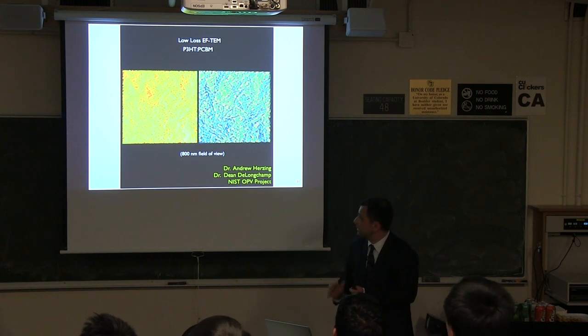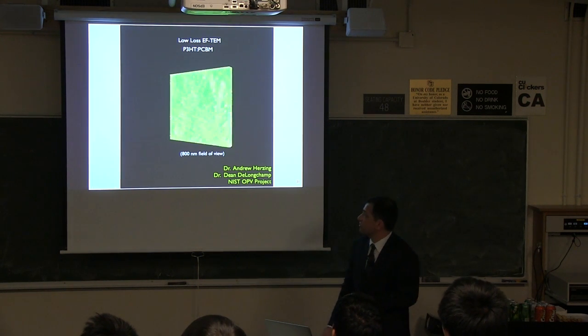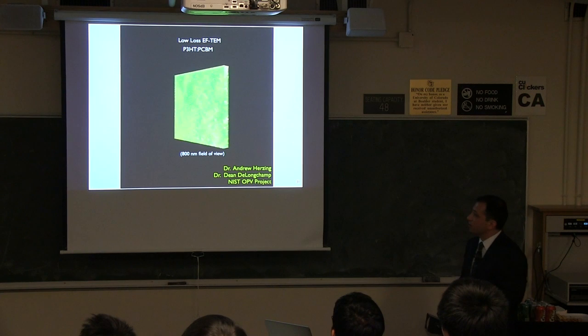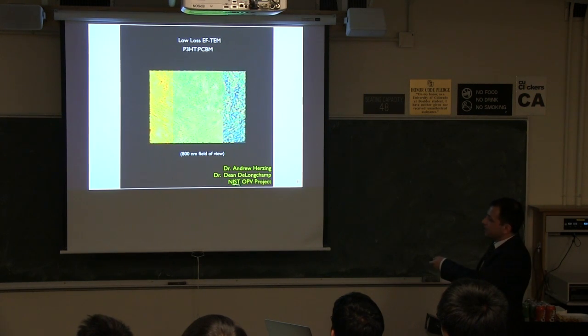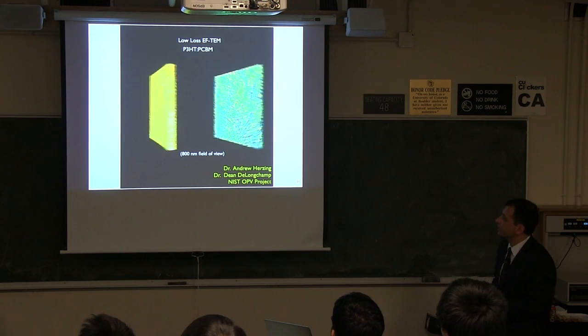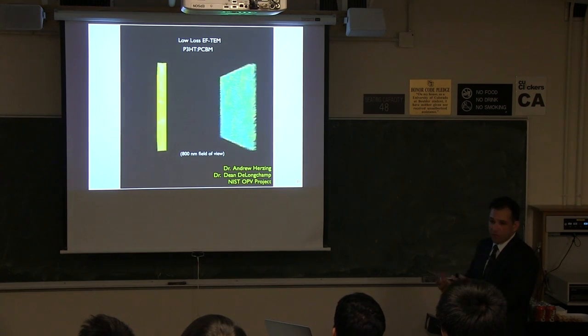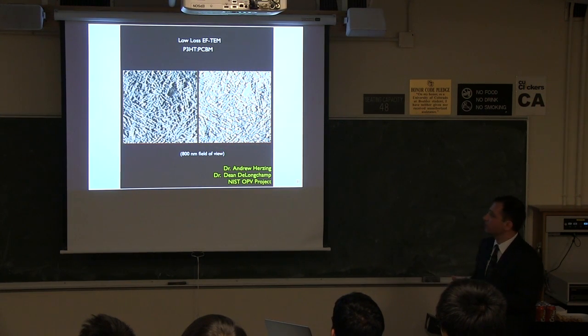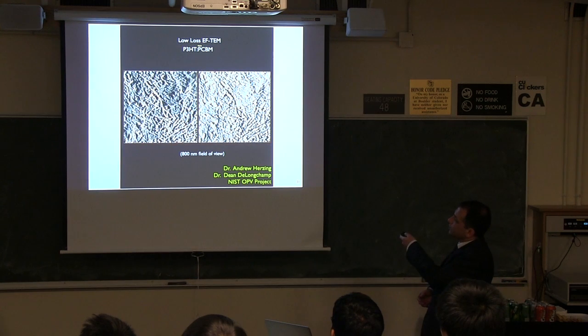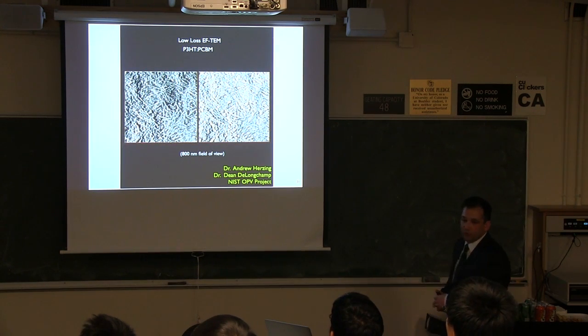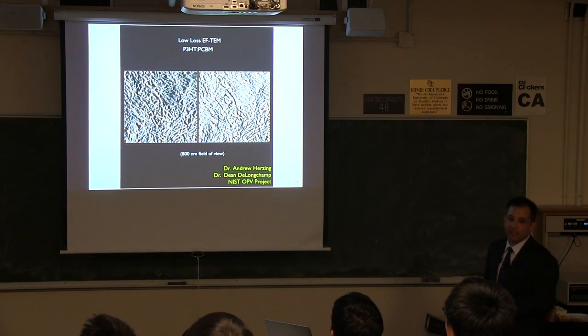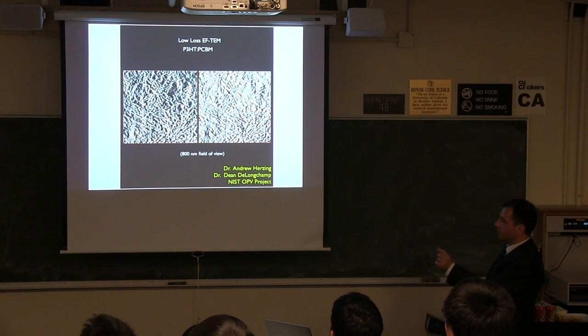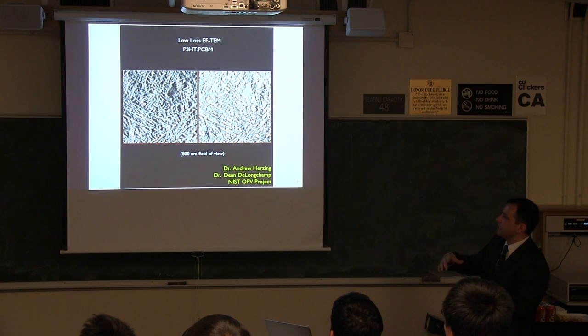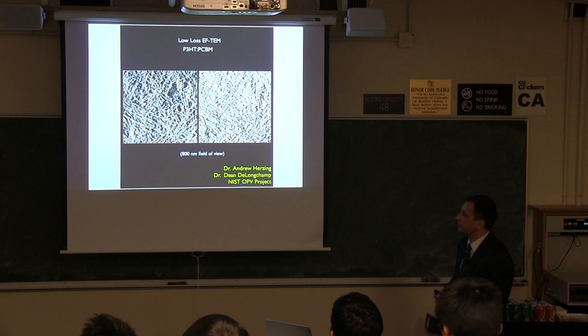So I mentioned that the mixing is very important, and the three-dimensional structure is very important. So there's a lot of technology being developed, a lot of it at NIST in Gaithersburg, but a little bit here in Boulder as well, to really resolve the donor-acceptor components in the material. So this is, again, using energy-filtered TEM, but here they're doing it as a tomographic technique. So what they do is make a little chunk of material, and they spin it around a central axis, and then come in with the TEM and scan across multiple angles, and then reconstruct a three-dimensional image of the material.